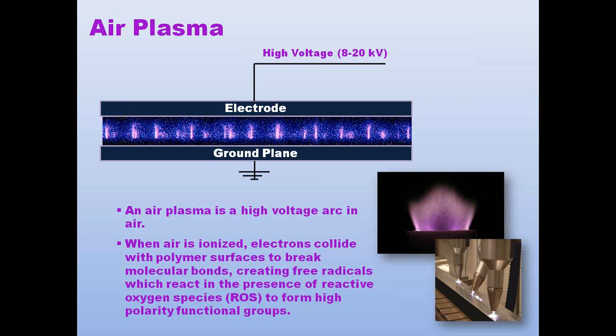It is nonetheless a high voltage arc. It is ionizing air as the medium between the anode and the cathode, or the electrode and the ground plane. When that air is ionized, we have electrons ultimately bombarding or colliding with the surface. In this case, a polymer surface breaks the existing bonds on that surface. It creates a free radical effect, which allows the reactive oxygen species that come from the ionization of the air to form polarity at the surface of the material. You can see by the various inset pictures that we've got different ways of delivering that discharge to surfaces. They can either be, again, arcs from an anode and a cathode, a blown arc from an electrode and a ground electrode, as well as a blown ion nozzle type delivery method.